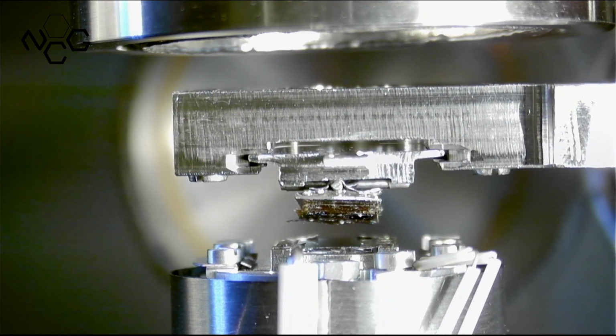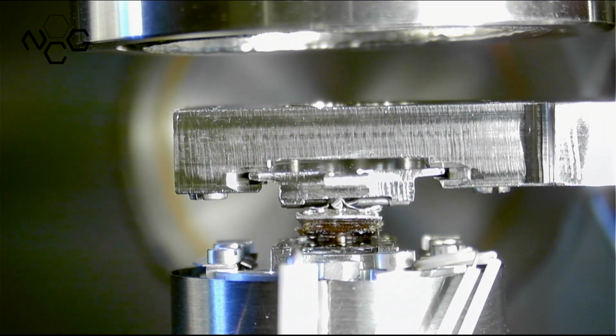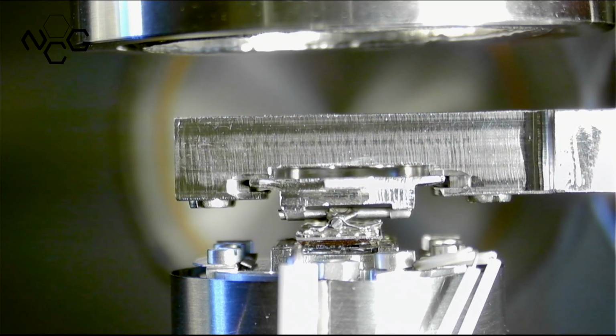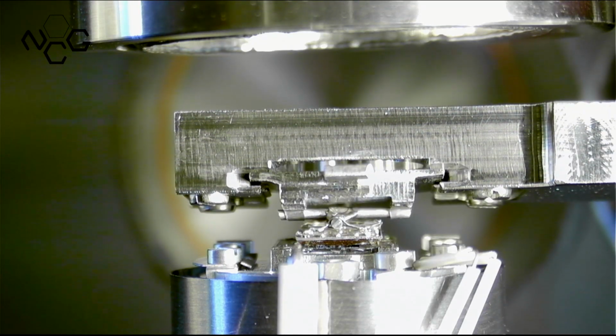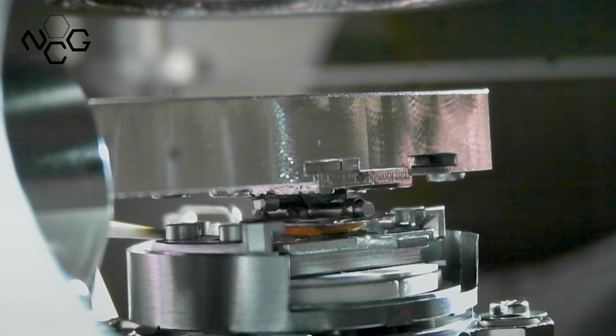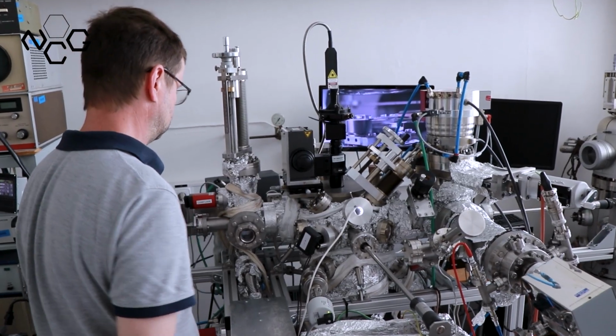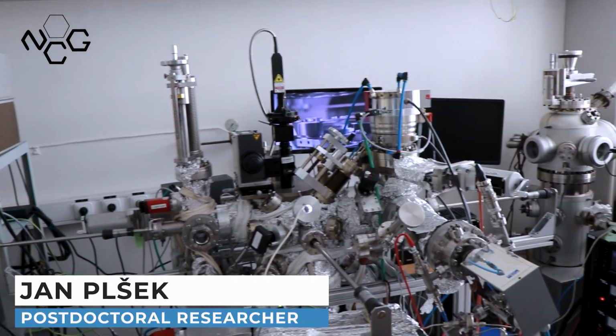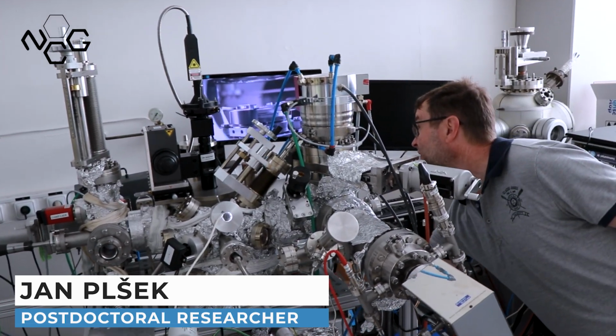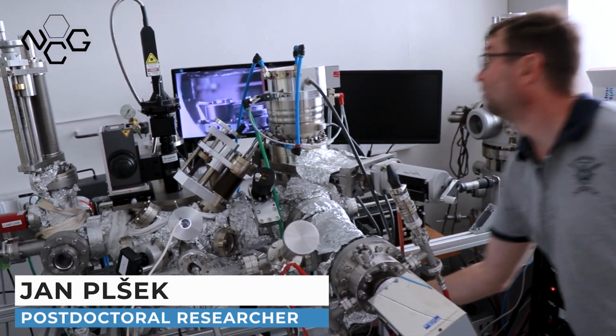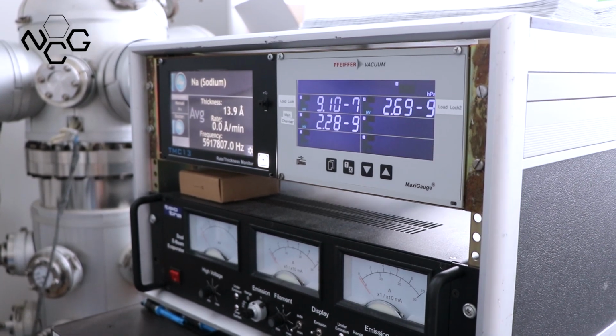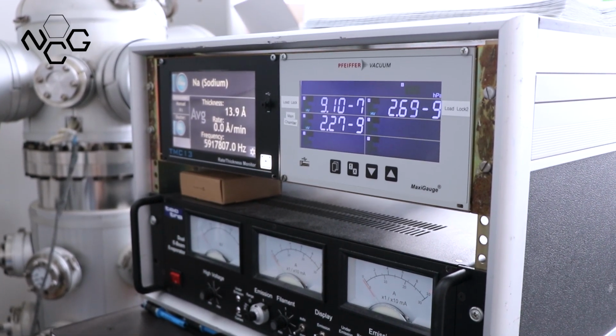Using this machine, we produce single-layer 2D materials, semiconductors, insulators, magnets, and superconductors by mechanical exfoliation on different metal substrates inside an ultra-high vacuum, in short UHV, where the air pressure is maintained at 10 to the power minus 10 millibar, which is 10 trillion times lower than the atmospheric pressure. Our main goal when we were designing this system was to reproduce all individual steps, which are usually done during the exfoliation process in ambient conditions, in an ultra-high vacuum chamber.